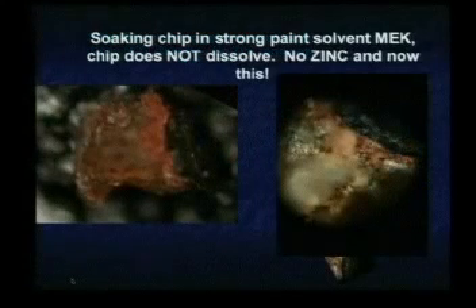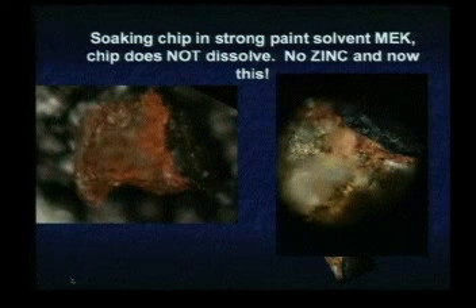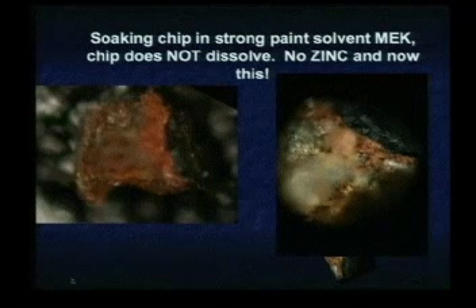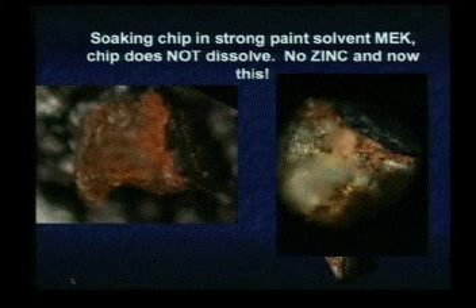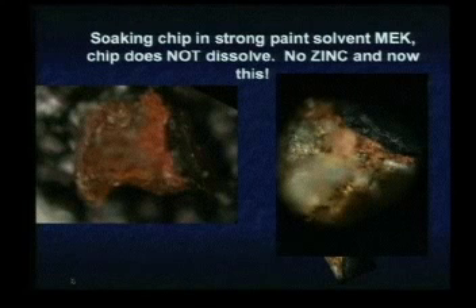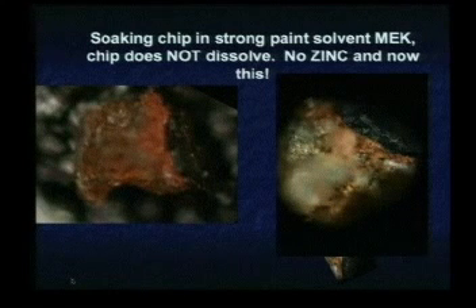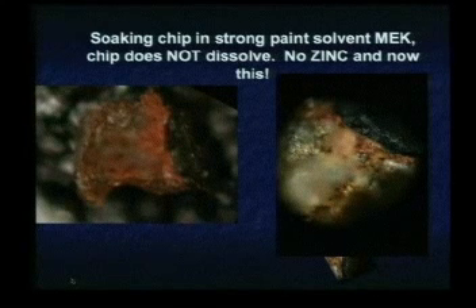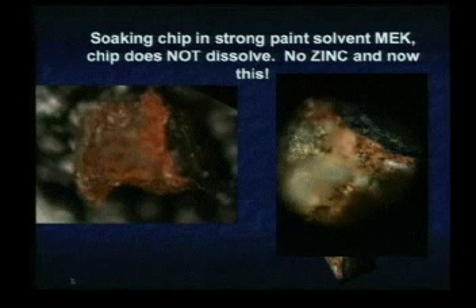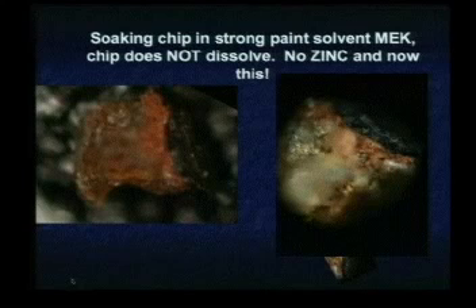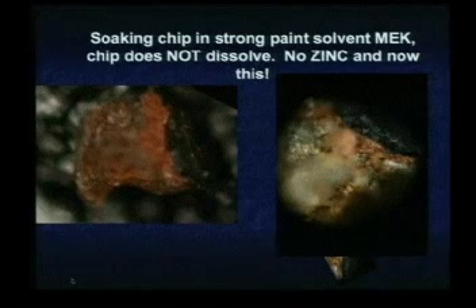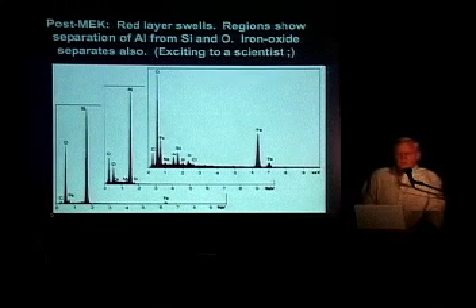Instead, what you see in these photographs is that the red portion swelled. The gray-black portion did not seem to be affected by the solvent at all. The red portion swelled, and can you see in the right photo the porosity that's now evident in the red material? This is primarily silicon dioxide, silica, with some iron oxide mixed in. And then on the left-hand side of the right photo, you see a silvery region. We found that the elemental aluminum separated out under the action of this paint solvent. Very interesting. Remember, there's a lot of carbon in here. The carbon does seem to break down. Okay, let's look at the data. Getting ahead of myself. This is in the paper.